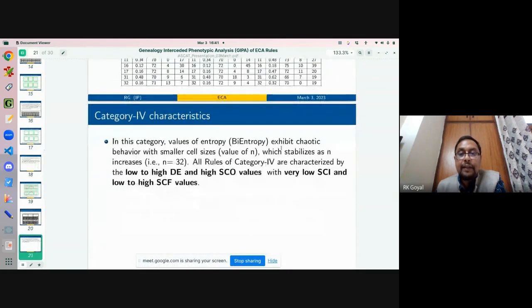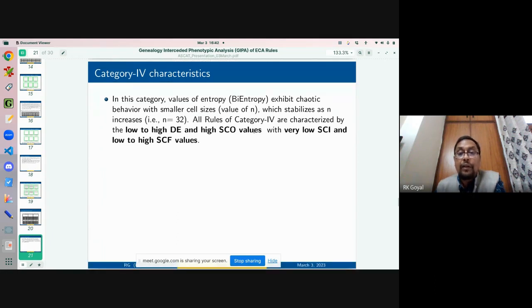Category 4. In this category, the values of the entropy exhibit chaotic behavior with a smaller cell size, which stabilizes as the value of n increases. Initially we start with chaotic behavior, but then it gradually stabilizes as we increase the value of n. This is an underlying assumption of this study, and also one of its limitations: we assume that the largest value of n considered here is 32, and a pattern shall surely evolve if it exists for n equal to 32. All the rules of category 4 are characterized by low to high DE and high SCO values, with very low SCI and low to high SCF values.